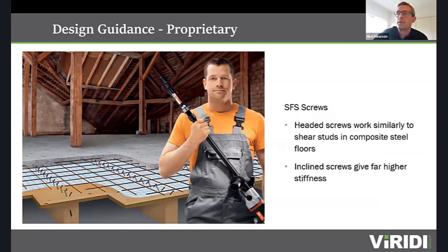This guy with his large tool is very happily selling the SFS inclined screws. They function like shear studs in a conventional steel concrete composite floor. They have a collar on them, and the head sticks out into the concrete. So when you cast the concrete on top, they form a shear bond between the timber elements and the concrete. There's a range of proprietary guidance available from SFS on these. What we found was the inclined screws give far greater performance than the vertical screws, just from the better alignment of the forces and actions present across that joint.